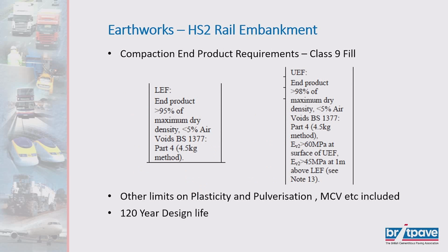Very high, one of the hardest specifications for earthworks for infrastructure in the UK. We have come across similar specifications under high bay warehouses for the likes of Tesco's, where they definitely don't want it to move. But in terms of infrastructure, one of the highest specifications, have a lower embankment fill, where you have to achieve greater than 95% MDD with less than 5% air voids on a 4.5k rammer, and the upper embankment fill, which is the top 5 metres of the fill. It's not just a 1 or 2 metre on top. So the top 5 metres of your embankment or below treatment is greater than 98% density on a 4.5k rammer, below 5% air voids, and an EV2, a stiffness, of greater than 60 MPa.